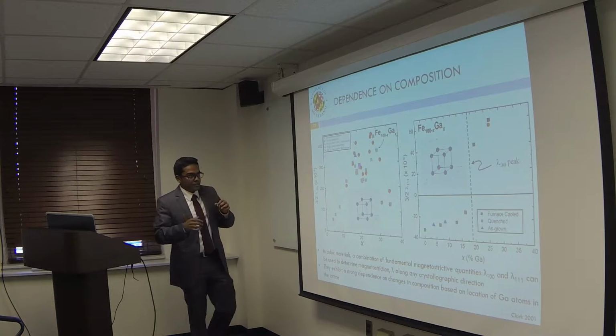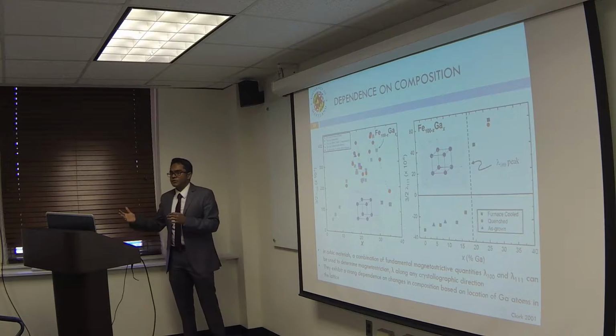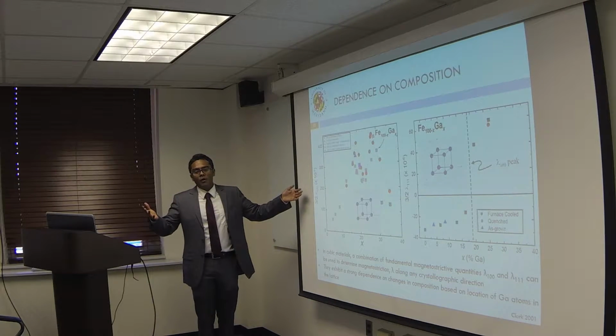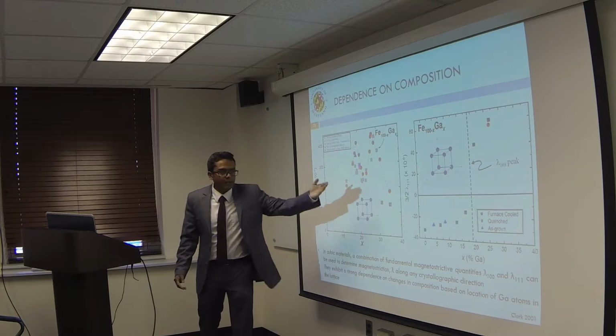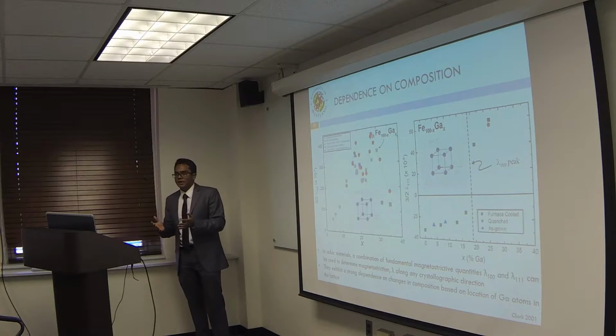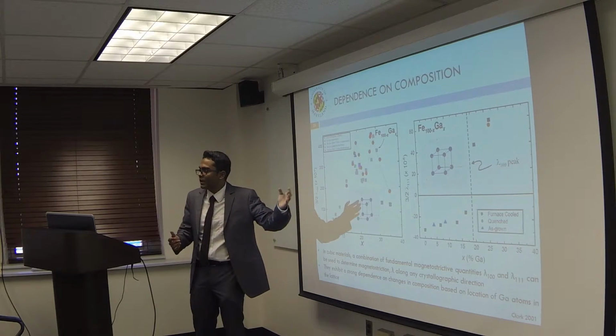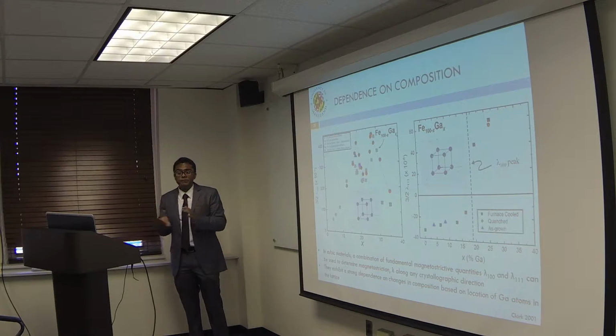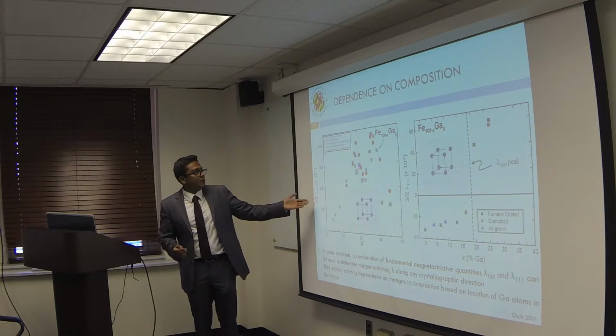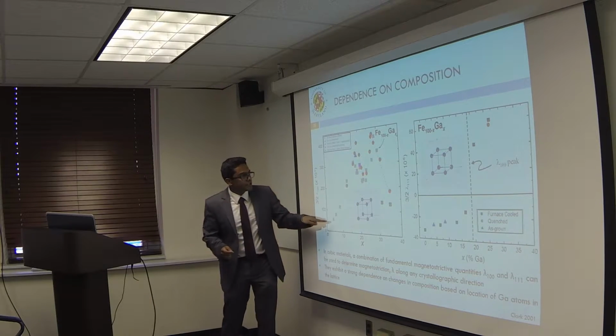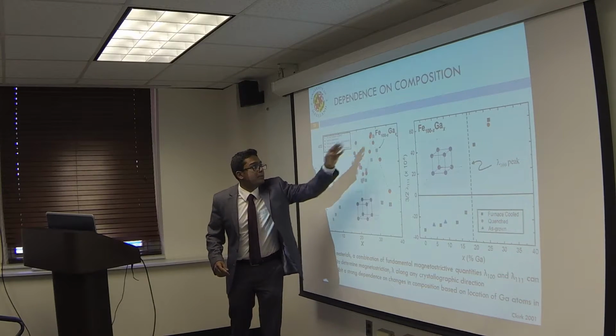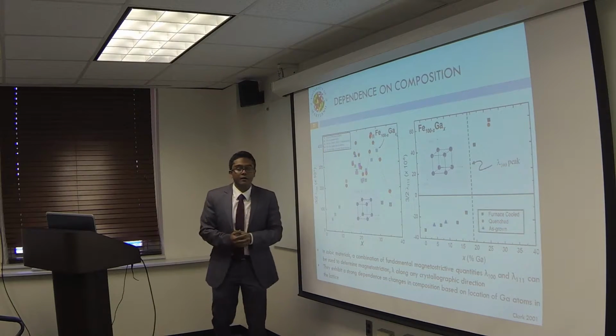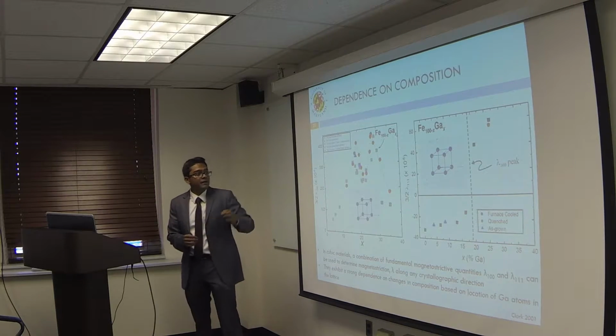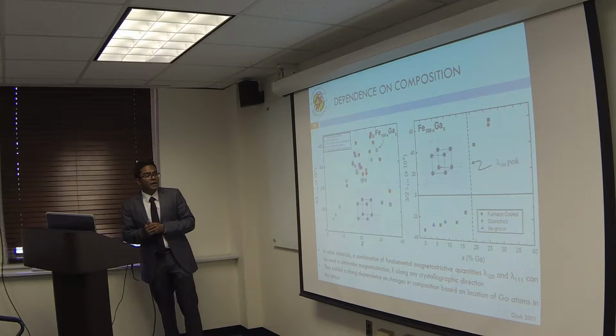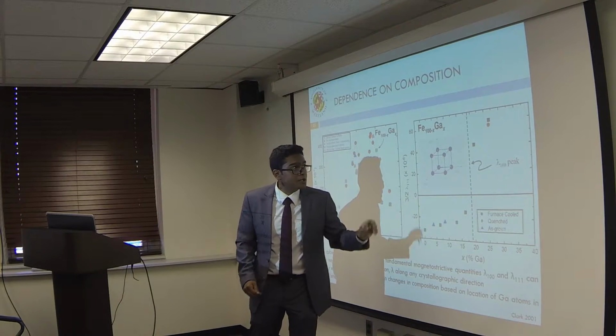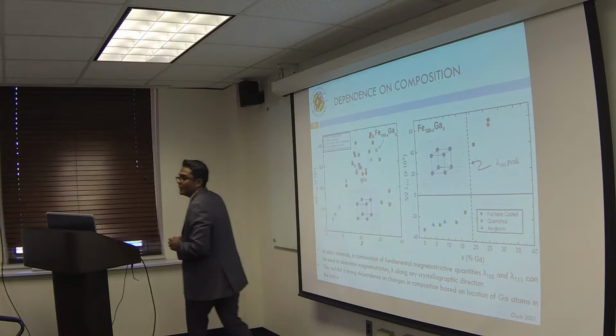So the way material scientists look at cubic materials when it comes to magnetostriction is they try and compute or determine the values of lambda 100 and lambda 111. These are called fundamental magnetostrictive quantities because once you know the values of lambda 100 and lambda 111, you can pretty much predict the values along any direction in the cube. So these were experimentally determined values for lambda 100 and lambda 111, and you can find that there's a strong dependence with the composition. We have two big peaks in the magnetostrictive values, and the value is around 400 parts per million, and this occurs at around 18% and 25 to 28% gallium content. And when we hit the first magnetostrictive peak along the 100 direction, we hit 0 in the values of lambda 111.